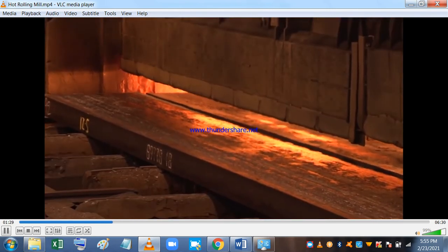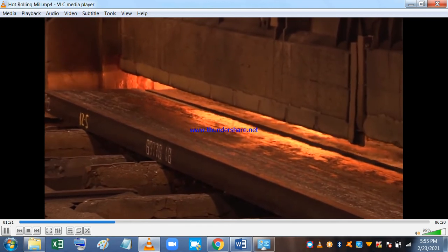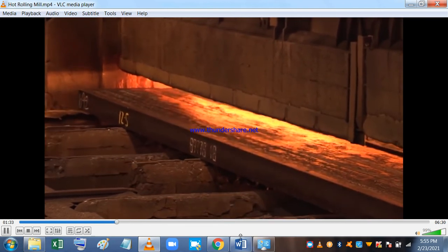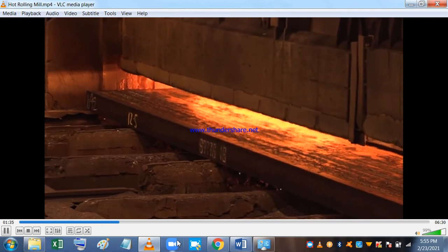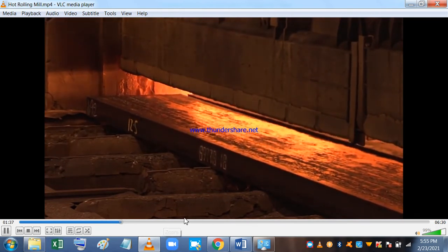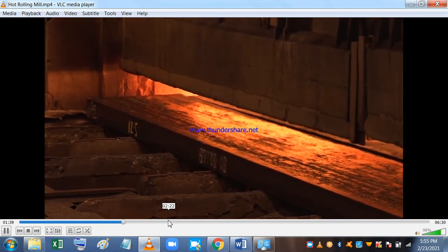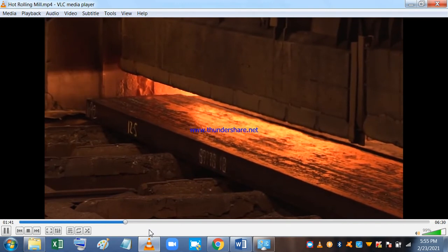These furnaces heat the material to about 1200 degrees centigrade. Two walking beam furnaces feed the material through the oven. These are the walking beam furnaces. The heating is especially important as it affects the properties of the material. If the material is not sufficiently heated, incorrect material properties will arise. This is due to oxides and nitrides failing to dissolve.